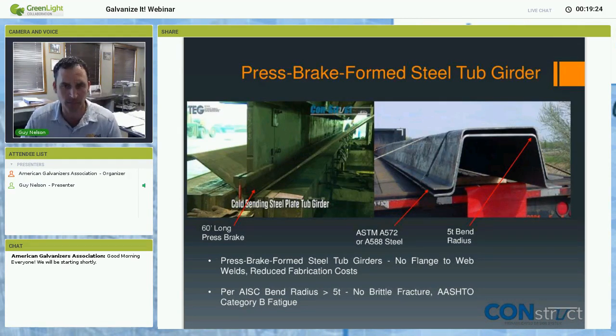The big advantage with the press brake form tub girder is that there are no welds, no web to flange welds, and the bend radius is per AASHTO and AISC requirements at 5 times the thickness of the plate, which means there's no brittle fracture when you are breaking these elements. Therefore, up to 60 feet long, you have one plate that is continuous without any welds, without any critical fatigue elements.